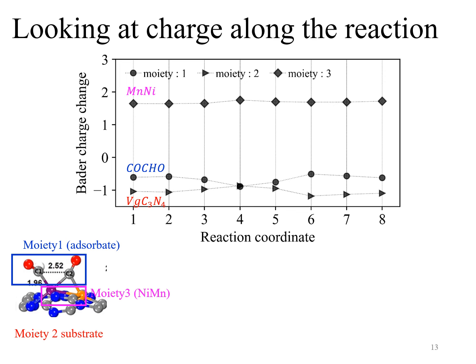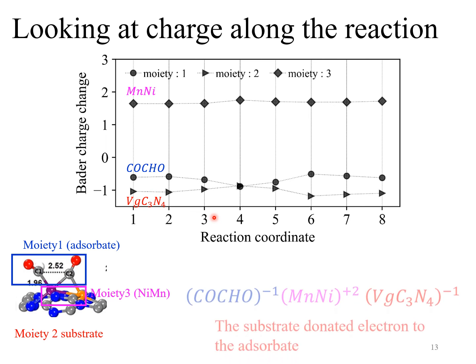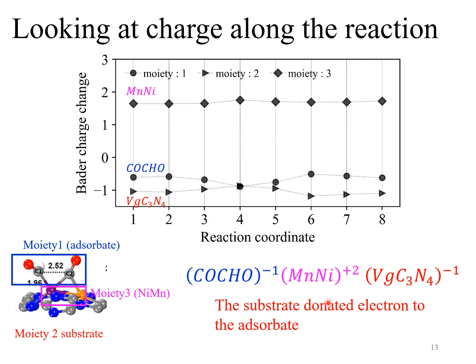We looked at the charge along the reaction path, and here along this reaction path, we separated to moiety 1, the adsorbate, moiety 2, the substrate, and moiety 3, the metal. And what we can see is metal is constantly around 2, while the adsorbate and our N-vacancy graphitic carbon nitride is close to -1. So we can see that the substrate has donated an electron to the adsorbate.